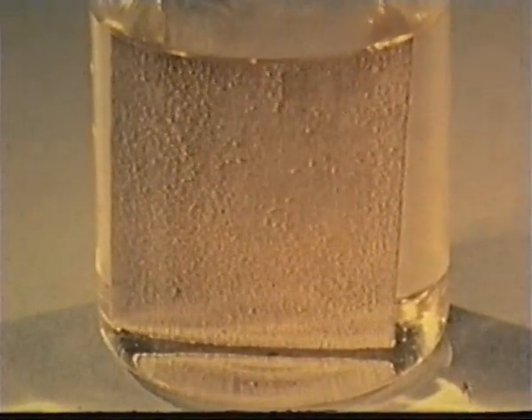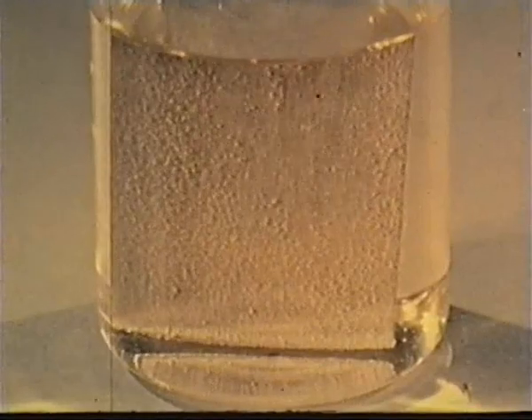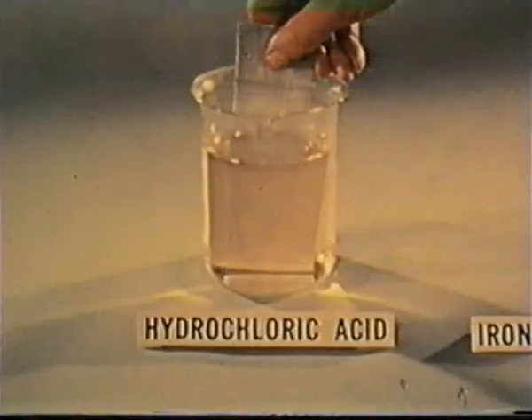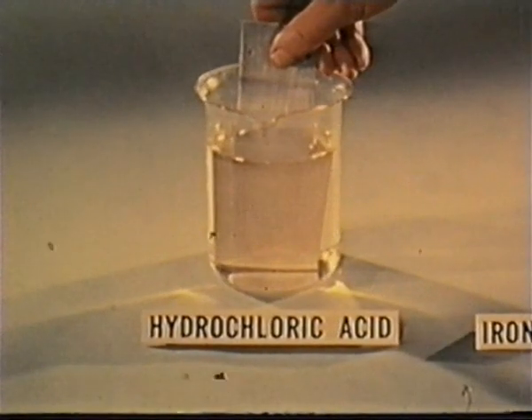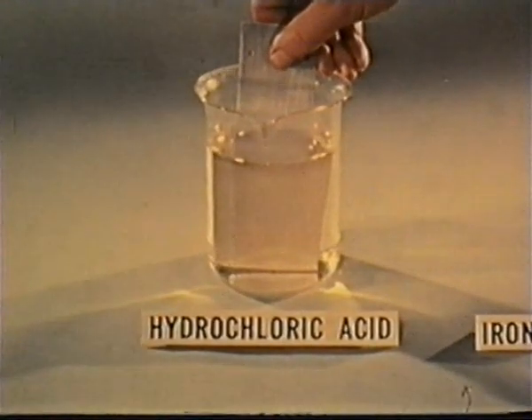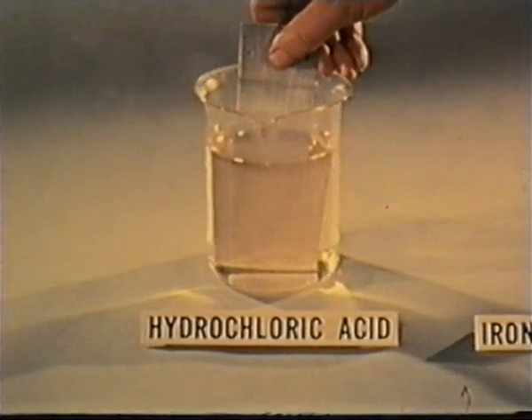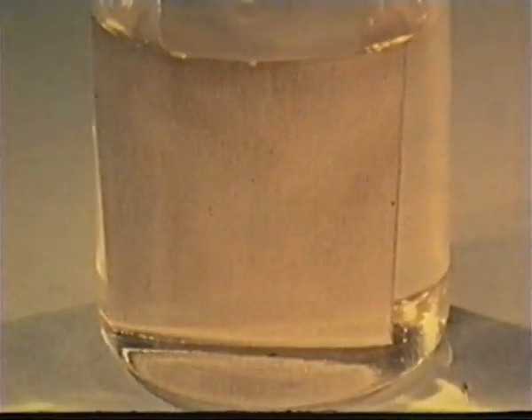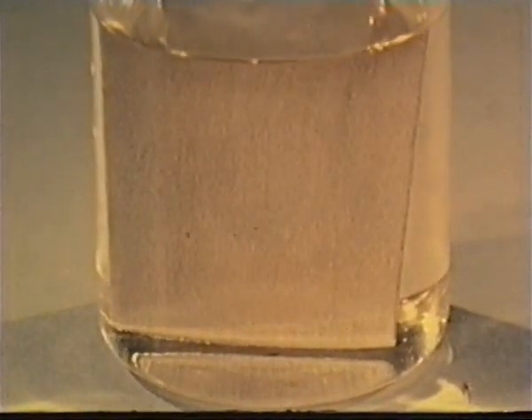The usual dissolution of the metal is occurring only at the anodes, with hydrogen bubbles forming only at the cathodes, even though it may appear that they are being released all over the surface rather than at well-defined cathodic areas. The anodic and cathodic areas shift from time to time. This permits substantially uniform corrosion to occur.